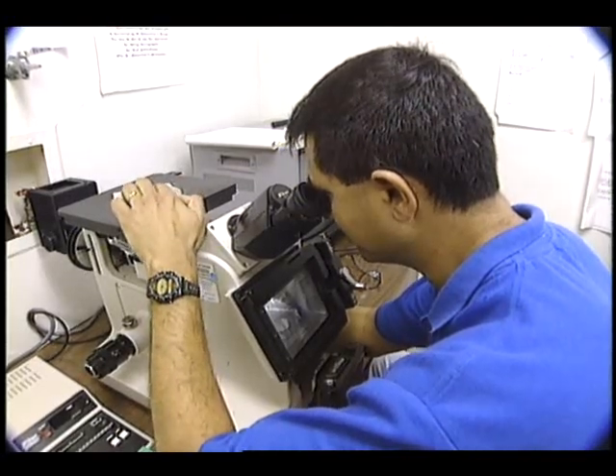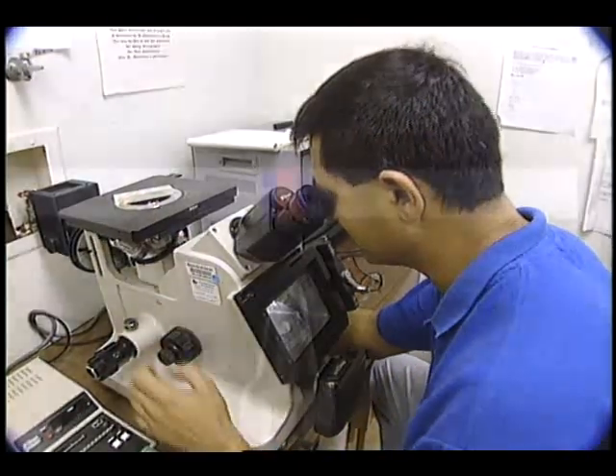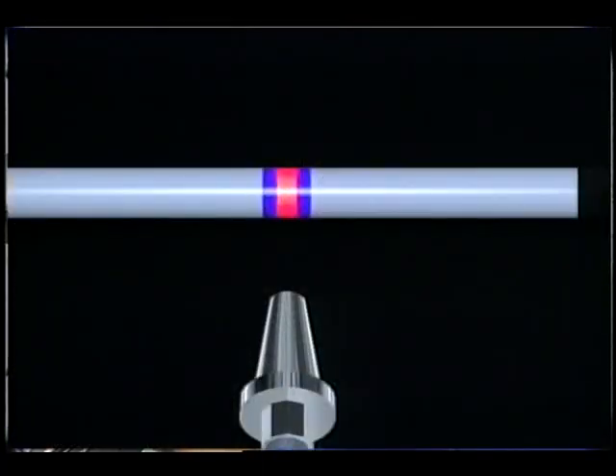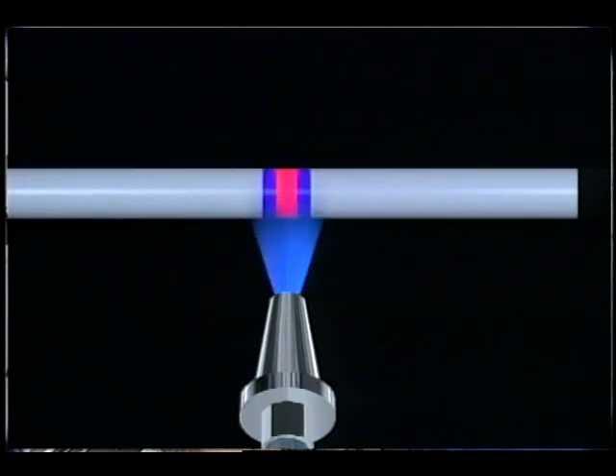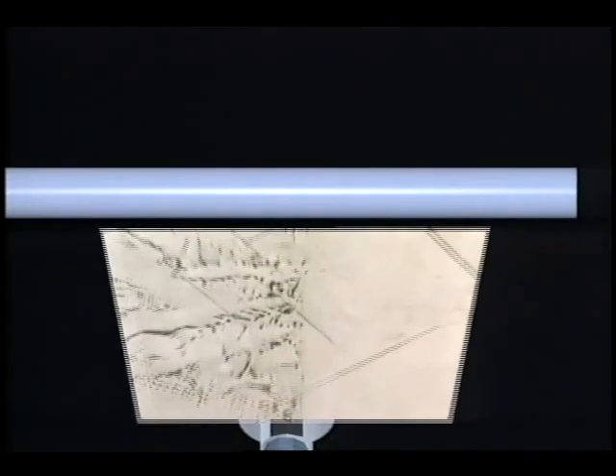At the conclusion of the experiment, the final 2 centimeters of one of the melted sample rods is gas quenched. The quenching instantaneously freezes the tin in the liquid. The quenched sample can then be analyzed to determine the at-temperature concentration of tin in the liquid.